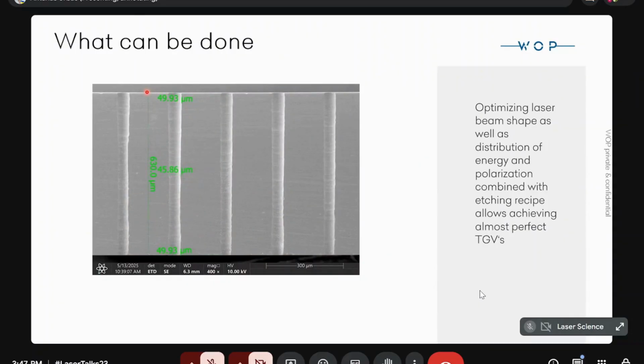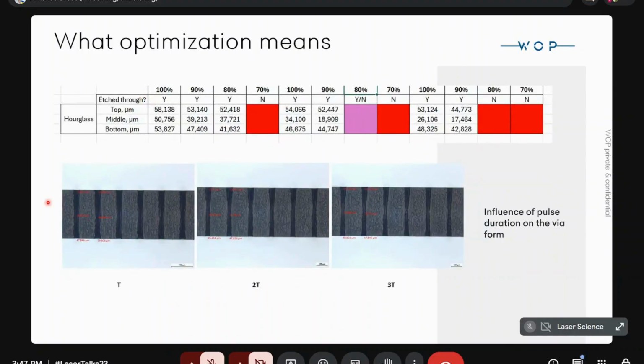As I mentioned, it should be optimized in energy, shape, and duration. So what does optimization mean? If we take the difference just in duration, these photographs show that difference: one length, double, and triple the duration of the pulse. You can see that with longer duration at the same energy, meaning that the peak fluence was three times lower here than here, the diameter of the via depends very strongly on the duration or peak fluence.